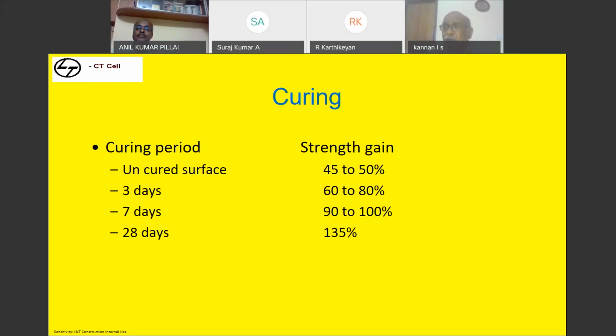You should not flood. Normally, what happens is you make a bund and flood water. Then subsequent activity has to happen, people will break the bund, the water will flow, and the concrete slab surface will become dry. It doesn't matter. Put somebody to sprinkle water always. Don't allow the surface to become dry. See that the surface is always wet. On a wet surface people can work. When water is standing, nobody is likely to work.